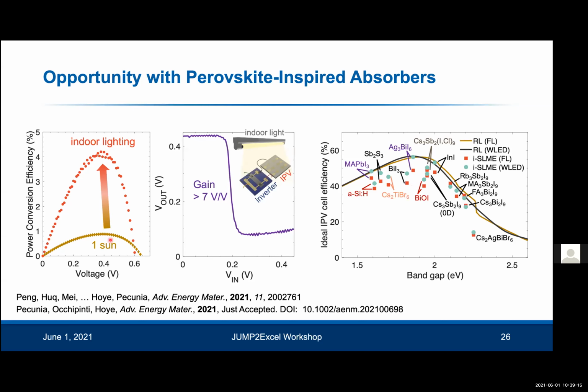And I show for one of the materials, bismuth oxyiodide, that just by taking the device indoors, the efficiency shot up by a factor of 5, simply because of the better spectral match of the absorption profile versus the emission profile of indoor lighting. And we showed that these devices were already sufficient for powering inverters, which is one of the components you would use in IoT electronics. And we showed that the optically limited efficiency limit for these materials can actually be a lot higher than for amorphous silicon, and also in some cases higher even than for the perovskites. So this is a new area of research that has a lot of promise.